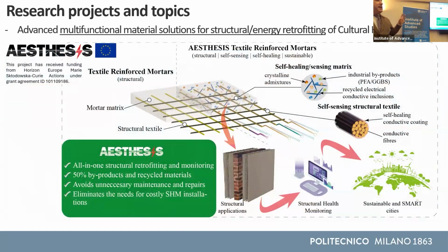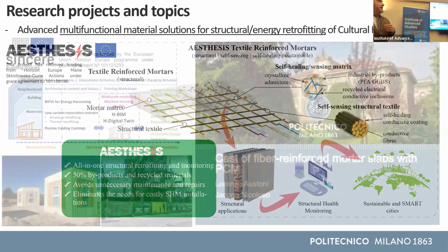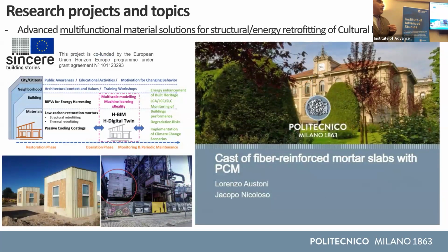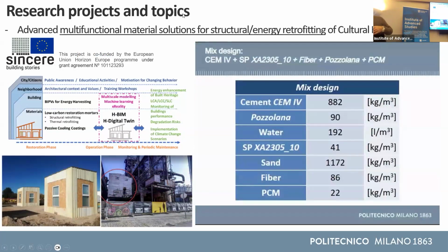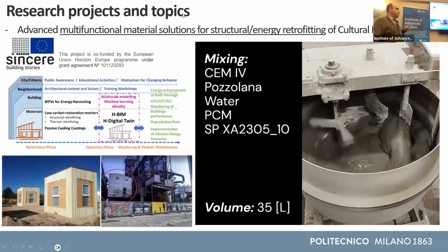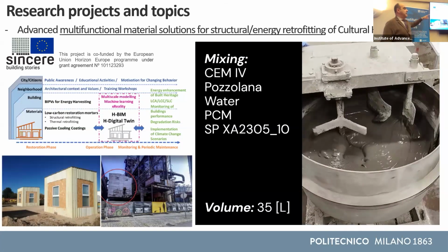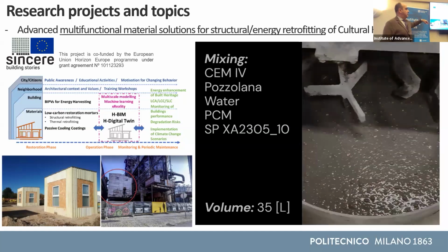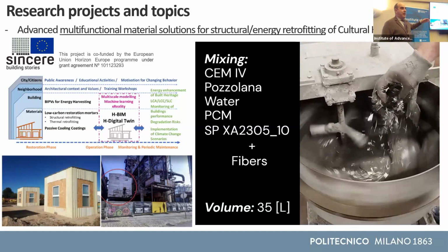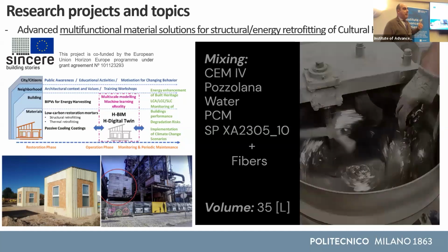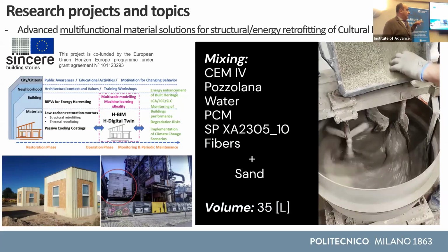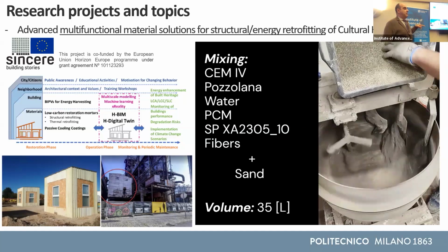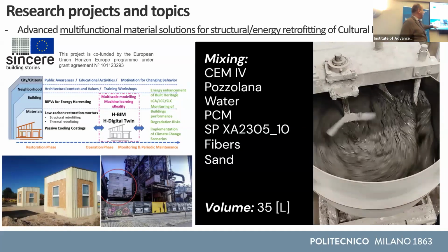We are trying from that experience now to embed in our retrofitting material self-sensing capability, so providing some conductivity to the material so that the material itself becomes a sensor. And we are now going to produce these materials, these UHPC, using CEM IV, using natural pozzolana, using amorphous alloy fiber, so trying to go lower on the embedded carbon footprint of the material, and try to incorporate phase-changing materials. We want to use this in the retrofitting.